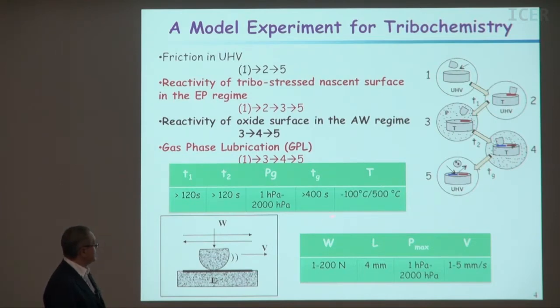Typically, we can change the temperature of the sample from minus 100 to 500 degrees, and the gas pressure can be controlled between 1 hectopascal and 2,000 hectopascal, so typically 2 atmospheres. And the condition here, this is a pin and disk, with a hemispherical pin, and the pressure is 200 Newton and so on.